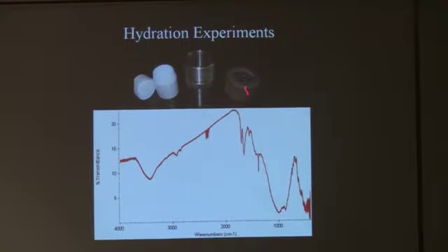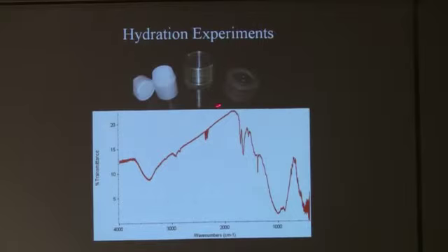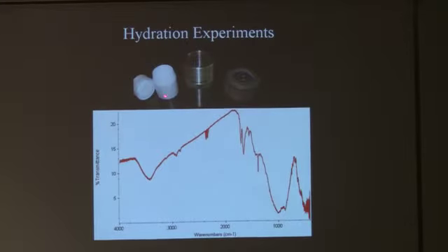So I said, well, I've got a bomb, and I've got an oven in a corner that I can just stick things in. So we loaded a piece of ordinary chondrite in here, in the Teflon part of the bomb, slightly basic conditions, 150 degrees, 1 month, 3 months, a year, and I have 3 still in the oven.